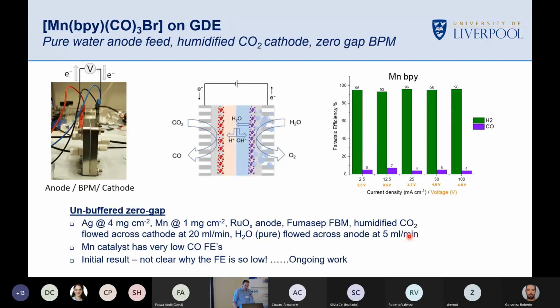So what happens if we put the manganese in that? It's a bit of a disaster. Bit of a bombshell, that. Fortunately, this isn't quite the end of the talk. So we get very, very low Faraday efficiencies, actually lower than we get with silver.